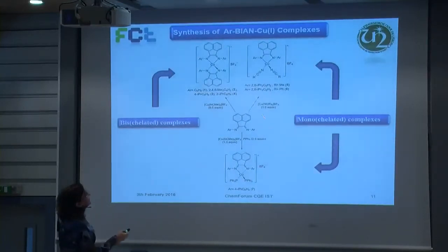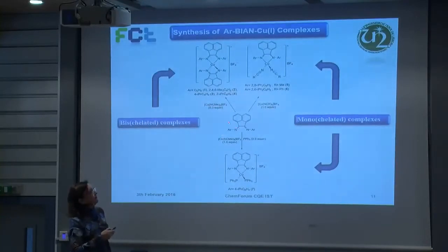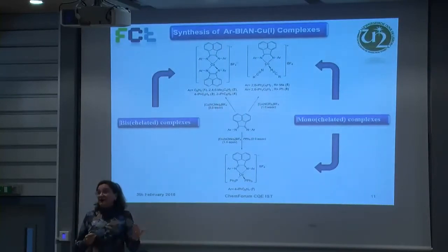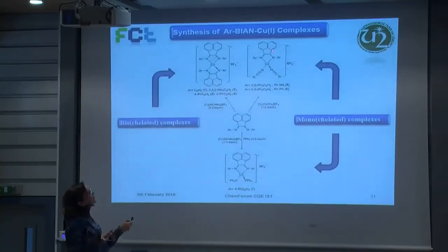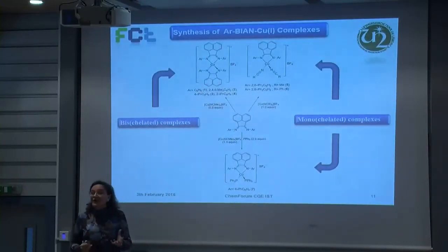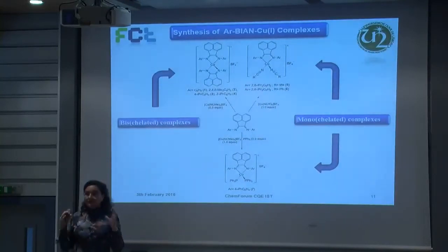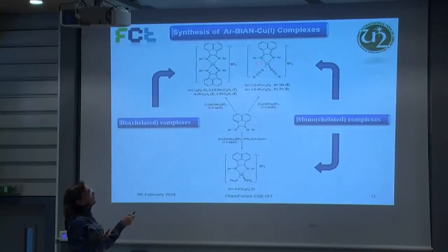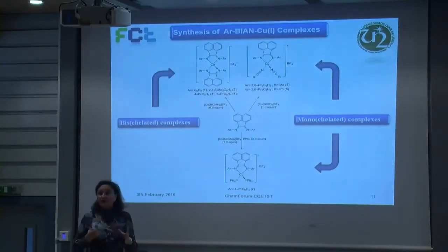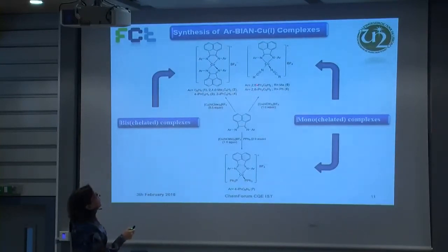For instance, the synthesis was based on the ligand plus a stoichiometric amount of the copper(I) salt. In this case, it is tetrakis(acetonitrile)copper(I) or another nitrile, for instance, benzonitrile. With the stoichiometric amount, you could get the bischelated complexes or the monochelated complexes, in which you have two nitriles coordinated to the copper. So we did a lot of syntheses modifying the R substituent by, for instance, 2,6-isopropyl, 2,4,6-trimethyl, and we also made these monochelated complexes.